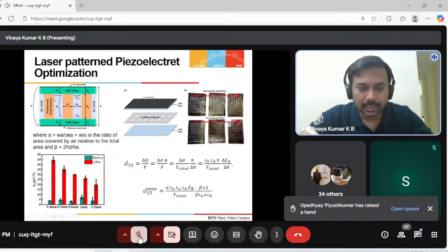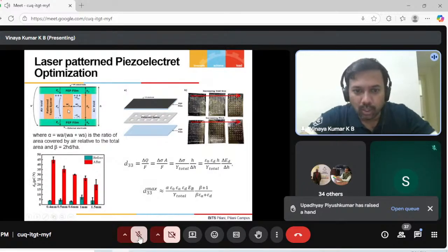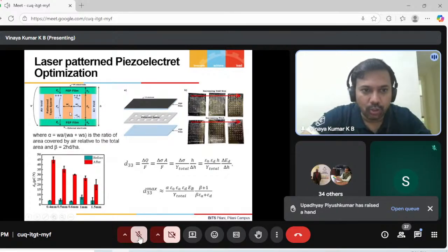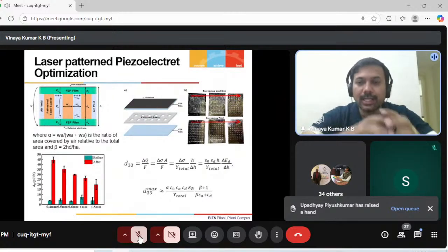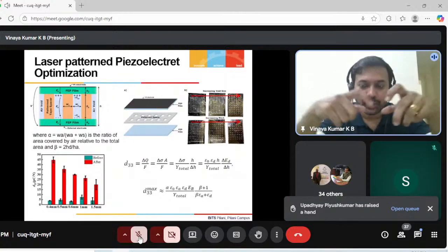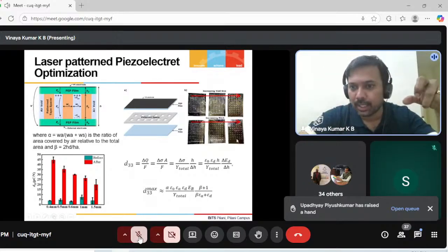We also did, like I said, to understand the effect of the void dimension on the piezoelectric coefficient D33, we fabricated the device using laser patterned void creation, and we were able to measure voids as small as 0.4 millimeter to 1.5 millimeter. As you can see, 0.4 millimeter gives a much higher piezoelectric coefficient because the density of the voids we have created is much more than with the bigger voids. The number of voids you see is much higher.